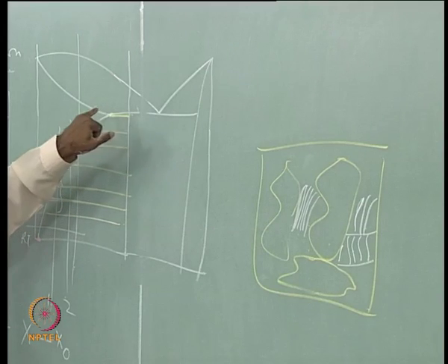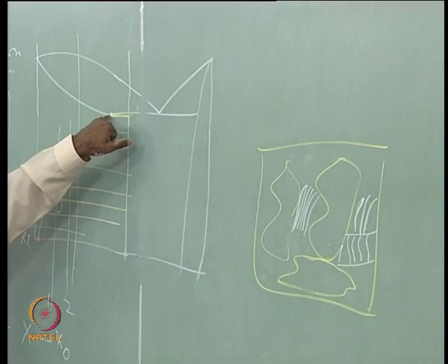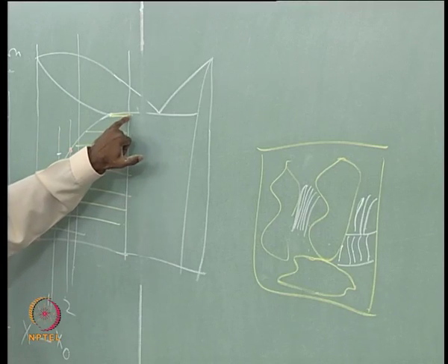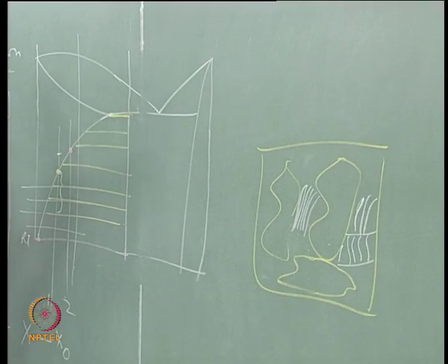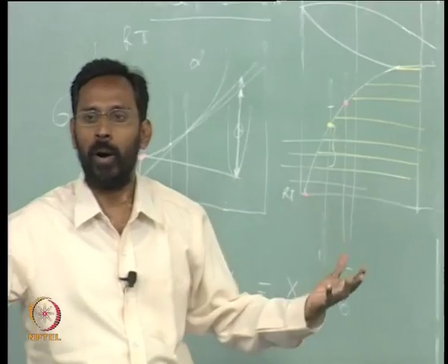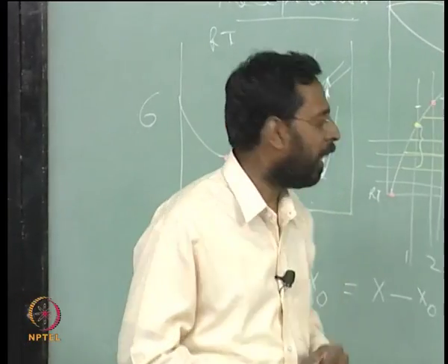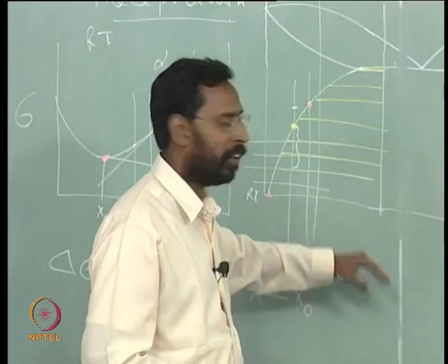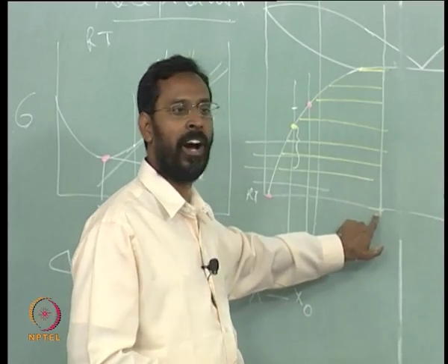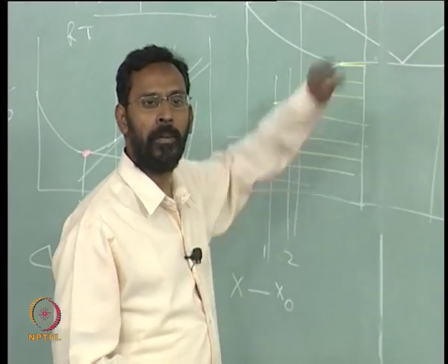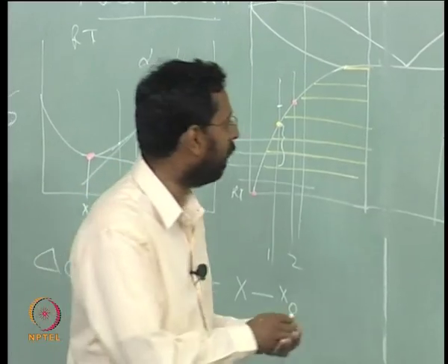Just after the eutectic reaction, alpha had this composition. So, if you have heated this alloy back to the temperature, you have more or less reached that particular condition, the existing alpha just after the eutectic reaction. When you quench it, you will have that alpha retaining all the copper content, and when you start heating it for the age hardening, that